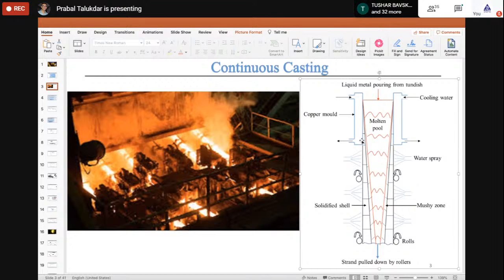So instead of having a copper mold of uniform cross section, industry tried to make a taper at the bottom of the mold, so that because of the taper, the air gap is as small as possible, and the heat transfer rate doesn't change, right? Because if there is no air gap, the heat transfer will be good. Now, whatever taper they are using is based on experience from their previous work, but there are no mathematical calculations done.